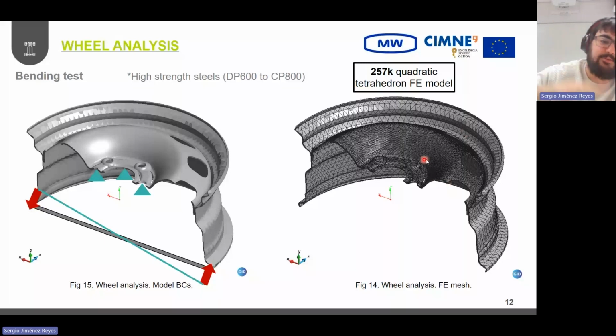And then we've performed this for several load levels, moment levels, and this is the type of result that we're obtaining. So we better capture this scenario with higher moment being applied in the wheel, but also in this lower case, experimentally, more dispersion is being reported, and our numerical result kind of fits within these results obtained experimentally. And this is the type of result that is obtained for the wheel demonstrator.